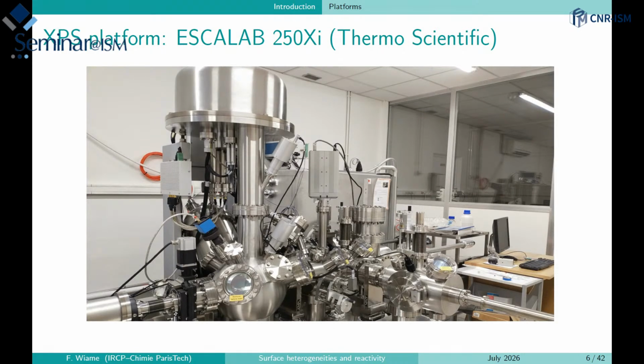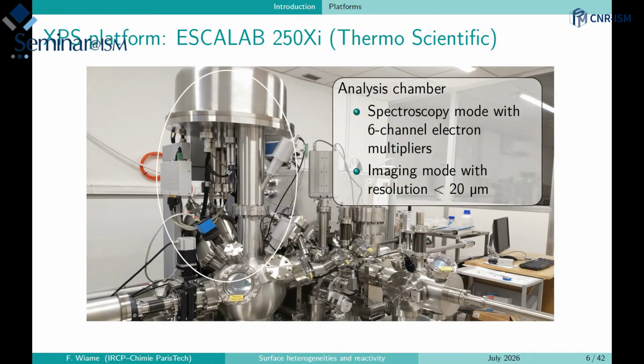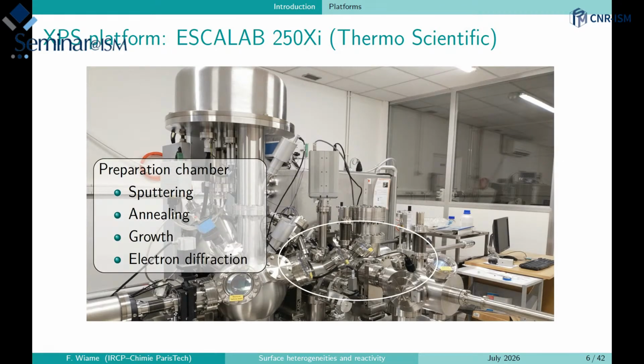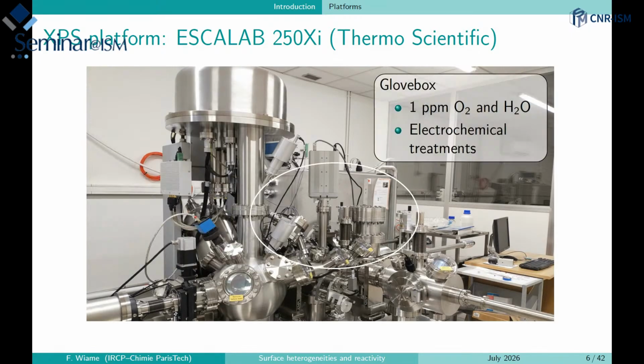So the techniques that we are using, here I will just present the ultra high vacuum techniques that we are using. So I will show you four different systems. The first one is a photoemission spectroscopy system, which is a commercial one, where we have six channeltrons and an imaging resolution of better than 20 micrometers. We have also connected to this a preparation chamber: sputtering, annealing, growth facilities, and electron diffraction. And connected to this, like on every one of our systems, we have a glove box where we can transfer the sample directly from ultra high vacuum to this glove box to do some electrochemical treatments and electrochemistry measurements, and then go back to the UHV.